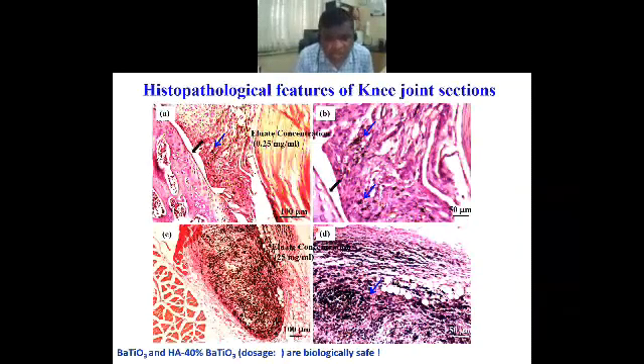Now, if you look at the much higher magnification histology images of the knee joints, or around the knee joint region, you can see there is some accumulation of the hydroxyapatite barium titanate, but associated with that accumulation, we did not find any signature of toxicity or inflammation.